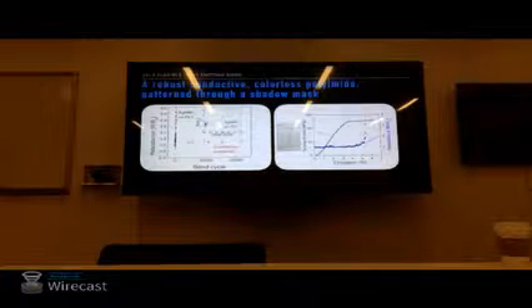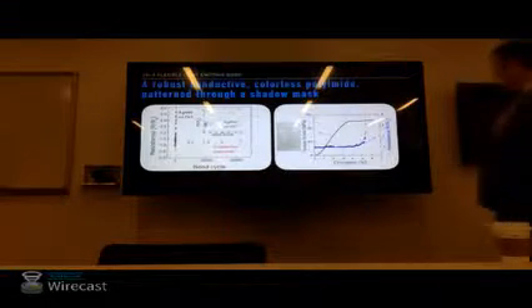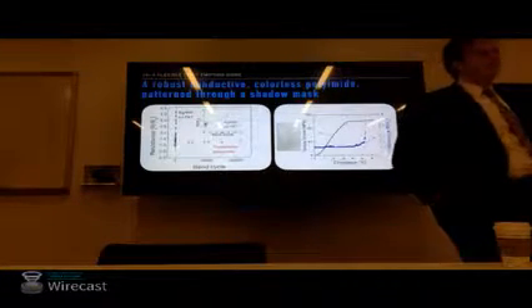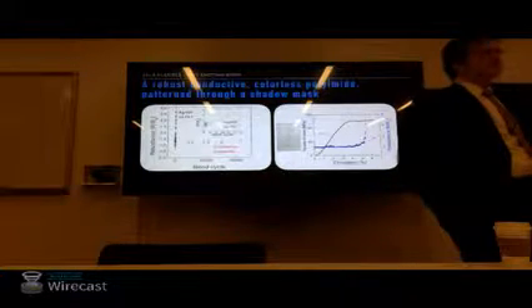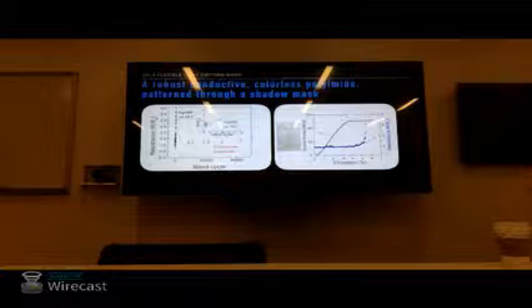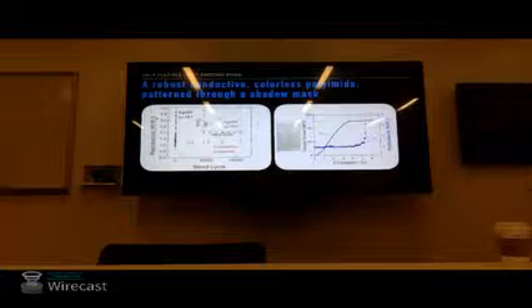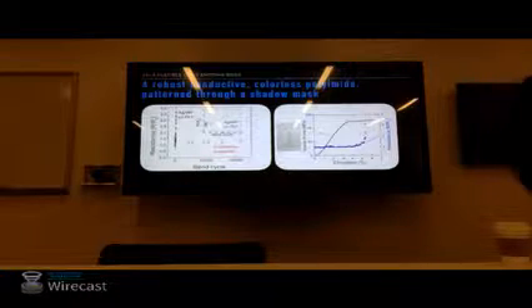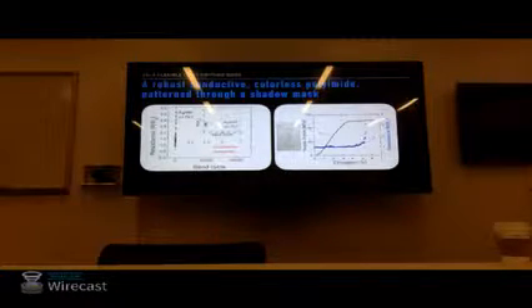If you want to make something flexible, are the strains really that high? We've basically done a tensile test, applying direct axial loading. That's correct. But actually, when you bend these structures, are the strains that high? Well, because they're so thin, they don't have to be. I think a lot of this is accommodated by it being very thin. If we have a thick chunk of polyimide, sure, it would probably fracture. So for bending, your strains would be much less because of your geometry.